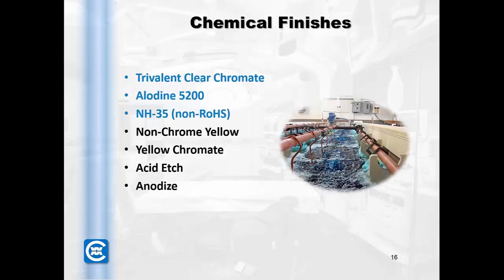Again, chemical finishes, we talked about this, but these are some of the more common ones that are used. A clear chromate, which is trivalent, so it's RoHS compliant. Alodine, which is another good pretreatment that's being used. A lot of times this is used prior to the E-coat process, but again, very good corrosion protection, relatively inexpensive, and a good pretreatment finish.